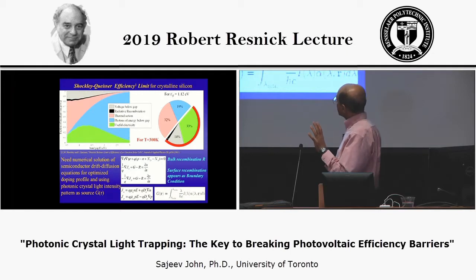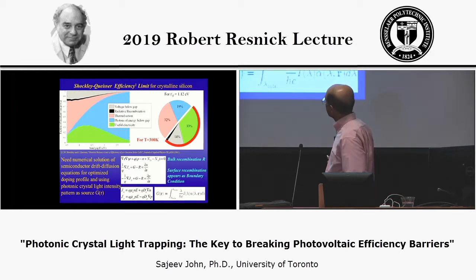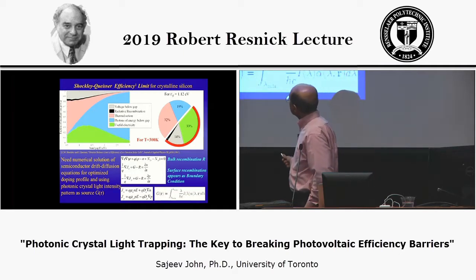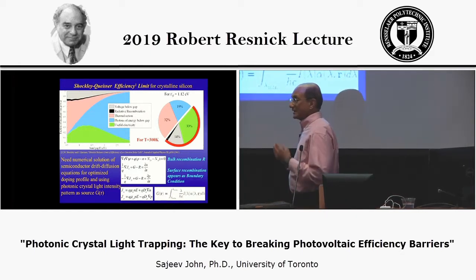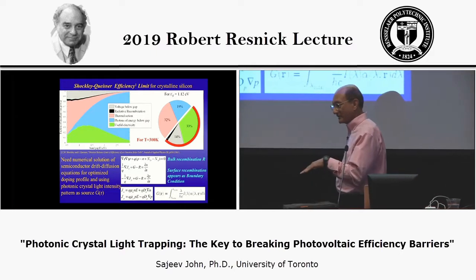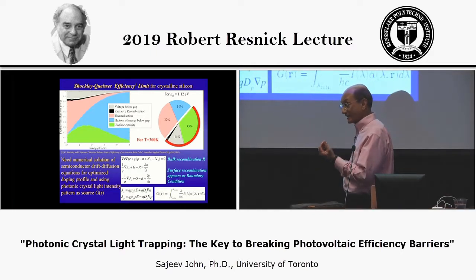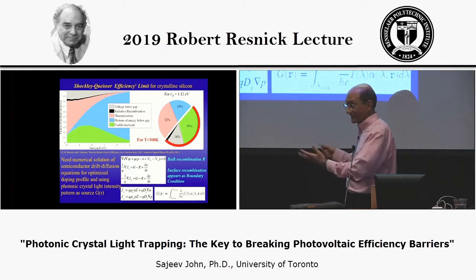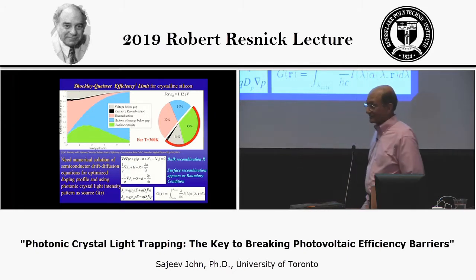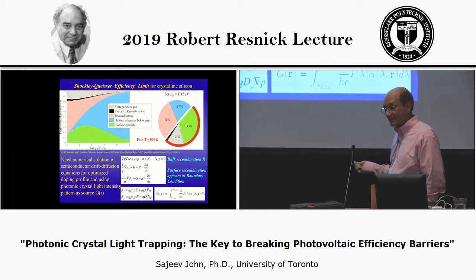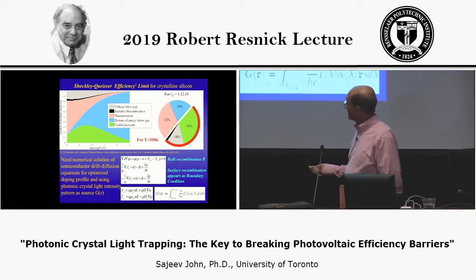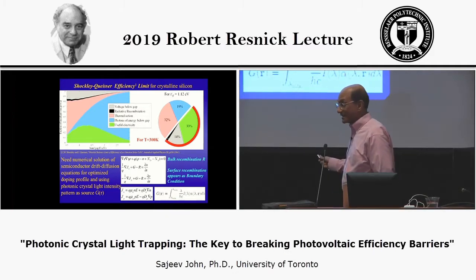Well, this is on a slightly larger scale than the scale of individual defects. So this is the density of donors, this is the density of acceptors, and this has a spatial profile that goes into it. Deep levels? Deep levels, okay, that is defined in terms of this recombination parameter. There's something called the Shockley-Read-Hall model for deep level defects, and that defines a carrier recombination lifetime that goes into this parameter. So that all enters into this parameter R, which can be a complicated function of carrier densities, etc. This is just R. Yeah, that is what is typically done in photovoltaics, and they've done a lot of comparison with experimentally tested solar cells by using these recombination models, and I'll talk about that.